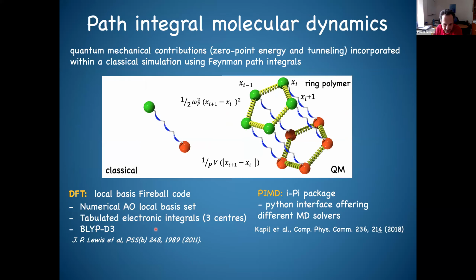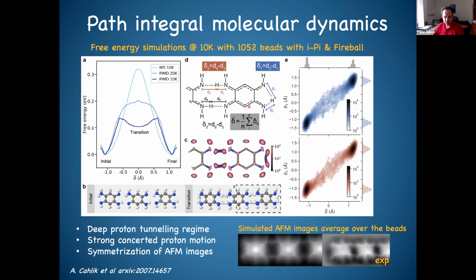To understand this from a theoretical point of view, we perform path integral molecular dynamics, because if we want to deal with this tunneling effect of hydrogen, we need to treat the hydrogen, the proton, quantum mechanically. And this is what is done in path integral, where a single proton is represented by beads, which are connected by rings, and this basically samples the wave function of your proton. So doing these simulations, what we first look at is the barrier to transfer from one side to the other.